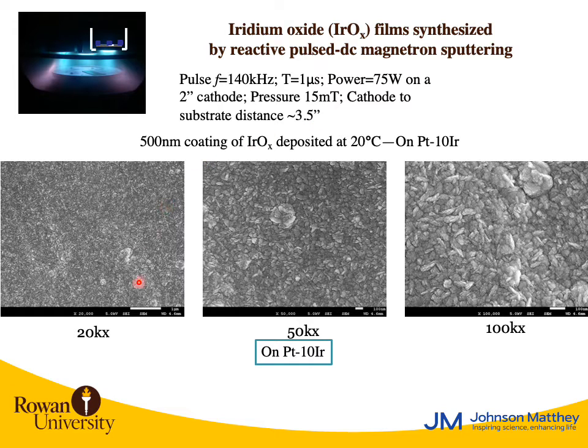So here represents a coating at 3 different magnifications. It's a 500 nanometer thick coating, deposited at room temperature, and the substrate here is that platinum 10 iridium alloy. So you see when you're zoomed out pretty far that the coatings are fairly uniform. When you zoom in, you see these sort of elongated grains. So here this bar is 100 nanometers in length.